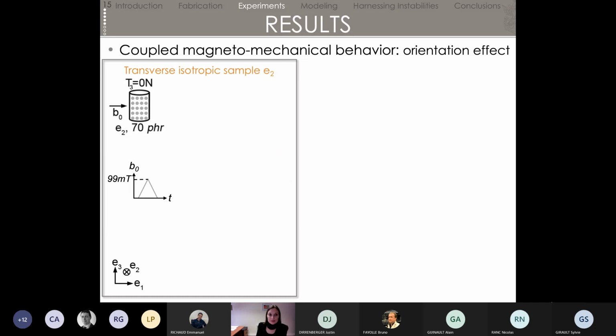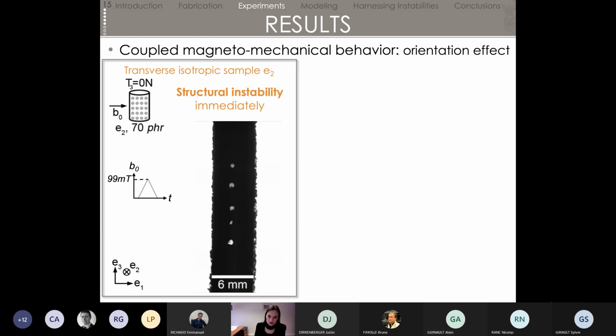So I'm going to start with the transverse isotropic sample, for which we have chains of particles. Those chains of particles are perpendicular to the magnetic field, and they're also coming out of the screen. What we're going to do is maintain the force equal to 0 throughout the loading. So it's like your sample is levitating inside the magnetic field. We do that, switch on the magnetic field, and immediately the sample is going to rotate.